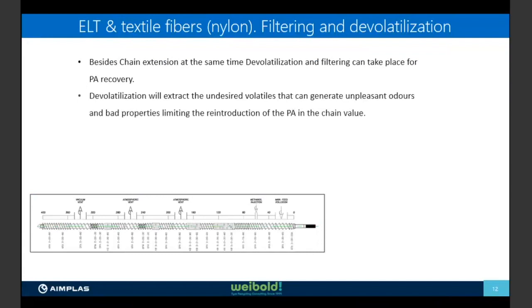Okay, and what is the devolatilization about? The devolatilization is a process where we use the extruder as some kind of extractor of volatiles that can be trapped in the polymeric matrix. Because of the use, because of the degradation, because of the recycling and the contact with rubber, polyamide can absorb different volatiles. Afterwards, when we recycle this polyamide, the volatiles, because of the mobility that they can have in the polymeric matrix, can be released. And these odors are probably not so pleasant. So one way of giving more market opportunities is to remove these volatiles.